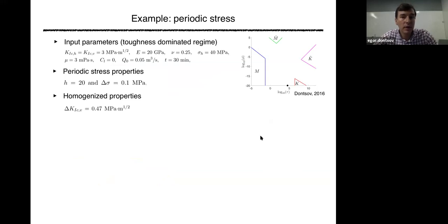And then examples, right? Again, with periodic stress, we need a toughness dominated regime. Here's our layer size, and here's our delta sigma, 0.1 MPa. Here the layer size is 20 meters, and the element size is 2 meters. So we have about 10 elements per layer, just to make sure that we have good accuracy. If you do all the math, you can compute the change in vertical toughness, about half a megapascal square meter.